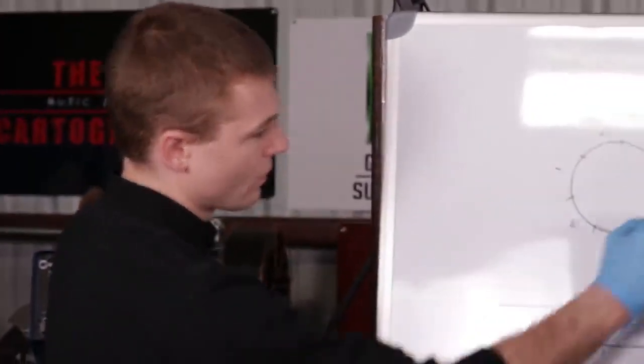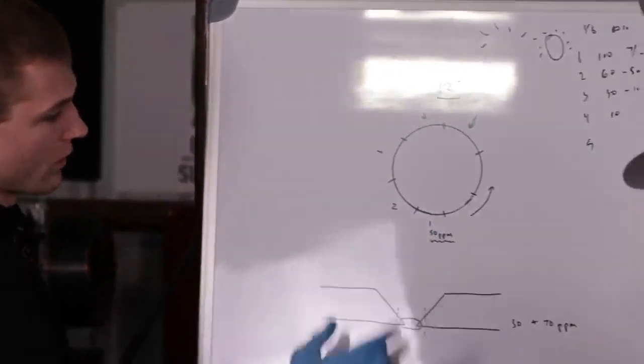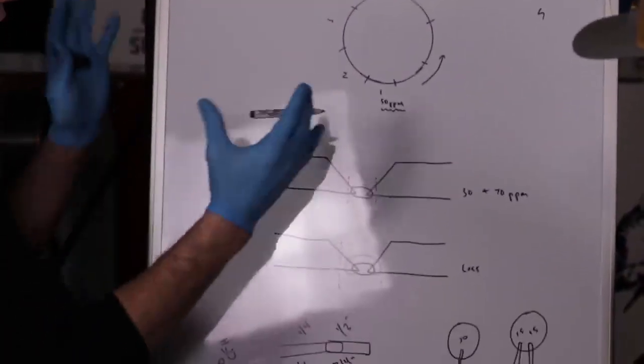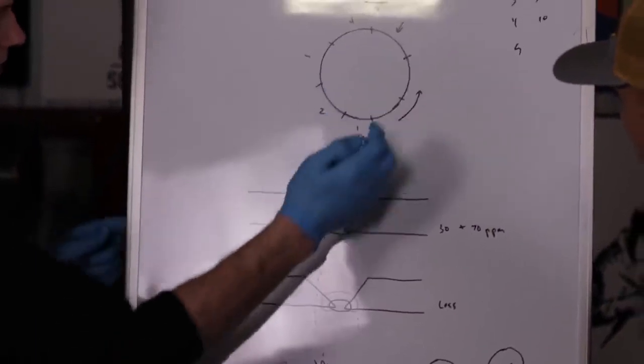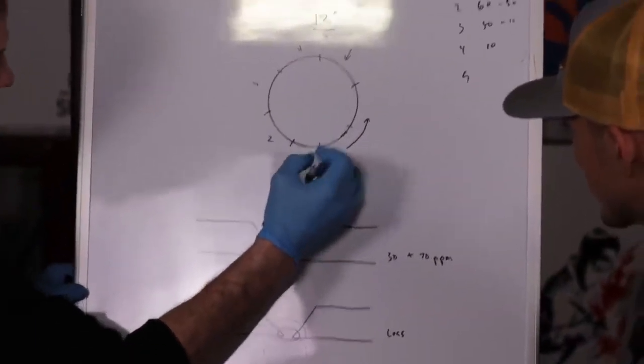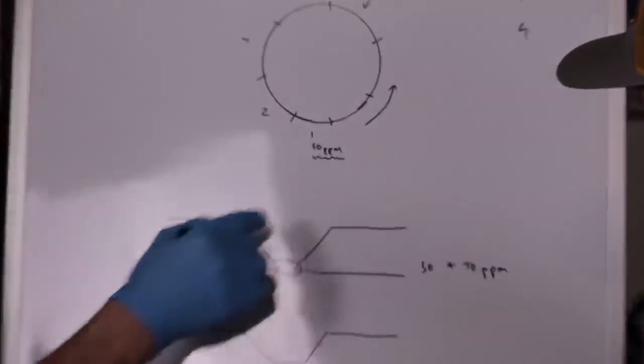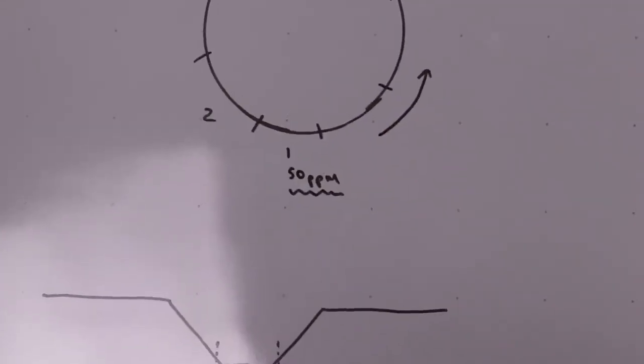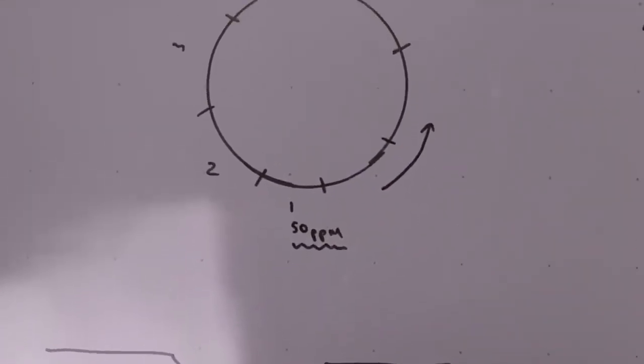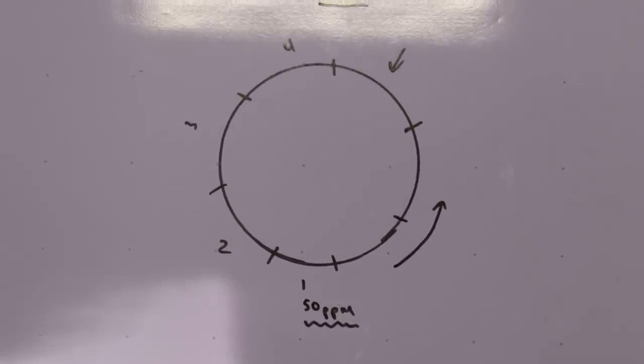Say, for example, hypothetically, when you have the whole entire weld all taped up, you're going to have the very worst parts per million of oxygen internally inside the pipe. And say you're getting 50 parts per million, 60 parts per million. If you wait a little bit longer, you'll start dropping slowly, maybe 40 parts per million, 30 parts per million, but you have to wait a little bit longer.